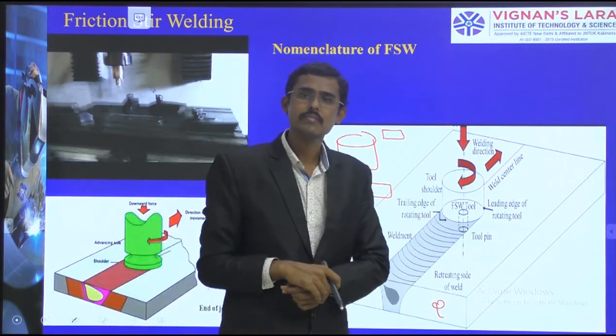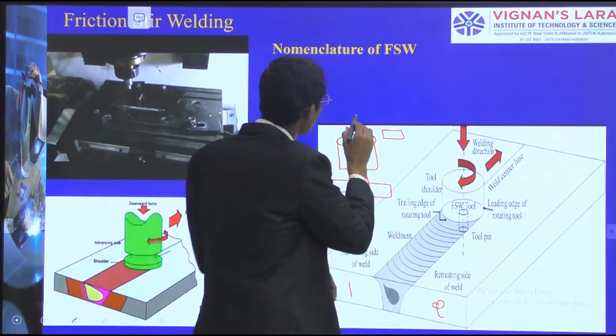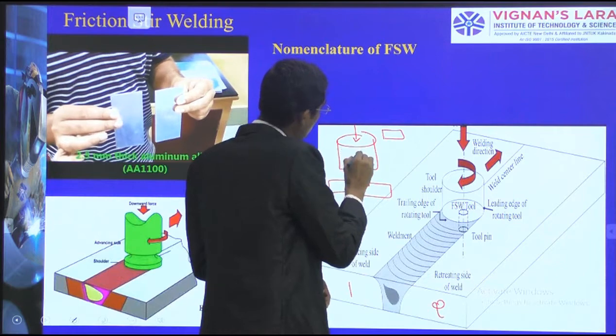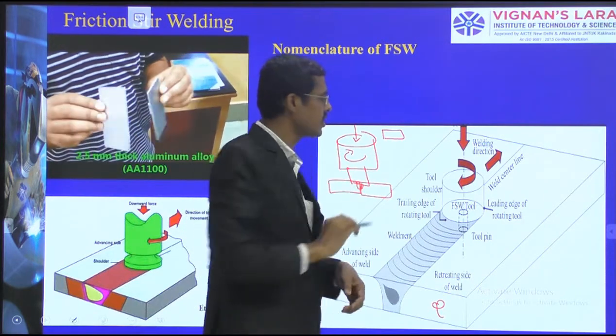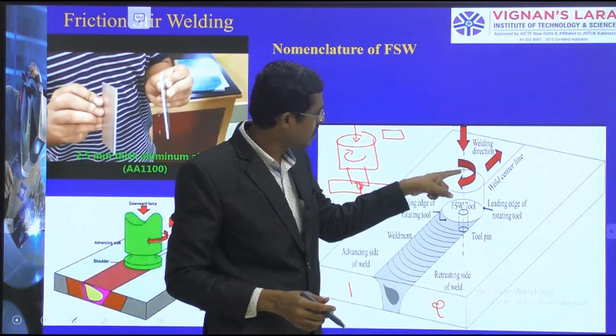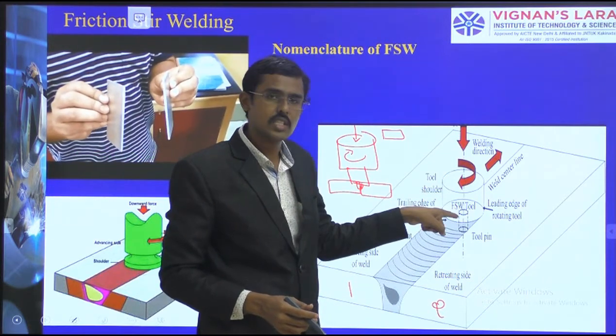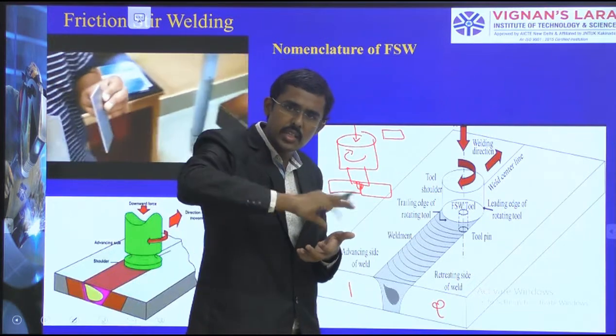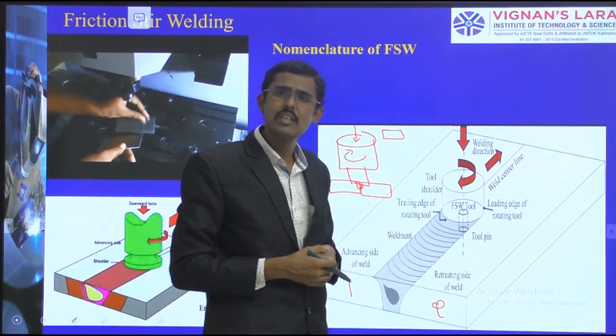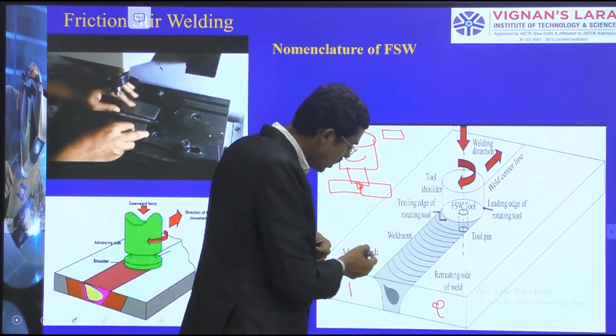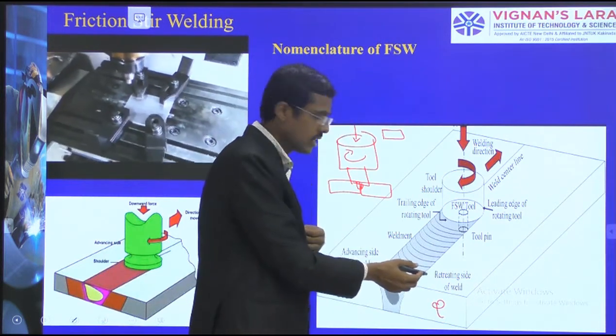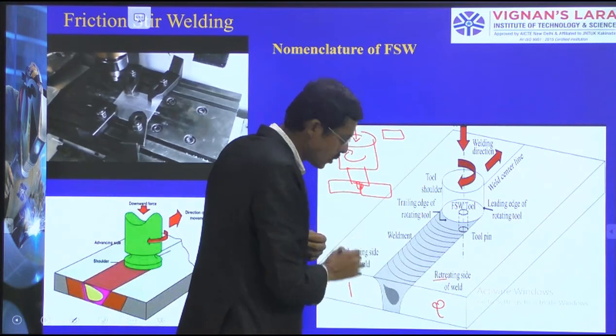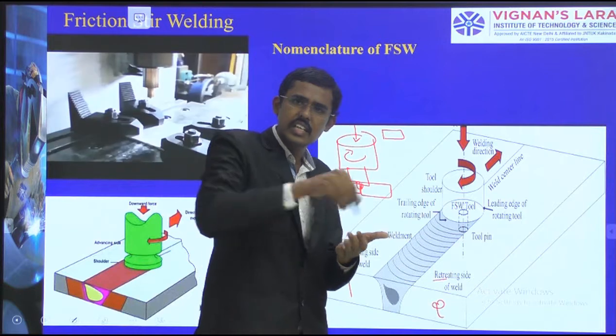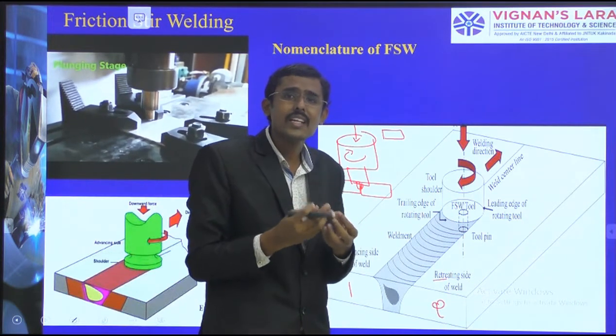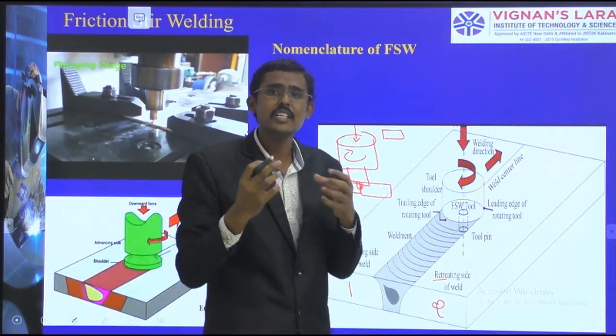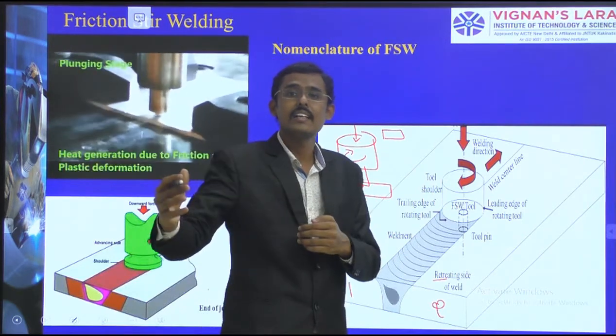After that, I am going to rotate with the application of pressure and rotation of this pin. Here the stirring will happen. The application of welding pressure and stirring action by the friction stir welding tool generates stirring action in the middle. Therefore, the advancing side material will go to the retreating side, and the retreating side material comes to the advancing side after the stirring action. Therefore, we will get equiaxed, finer grains. Finer grains are directly related to high strength.